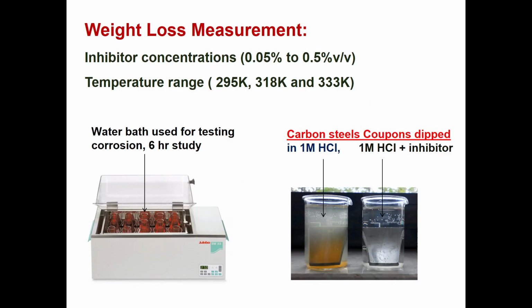Well, we utilized two methods. The first method was the weight loss method, in which we use different concentrations of the inhibitor from 0.05 to 0.5 volume by volume percent, and the temperature we tested at 295 to 333 Kelvin. You can see that we tested the blank, that is, without inhibitor, and then also with the inhibitor. You can even see from here that with this inhibitor it is a much clearer solution as compared to this one here, where corrosion is appearing. And we utilize a time span of 6 hours for every batch study, and we utilize this water bath.